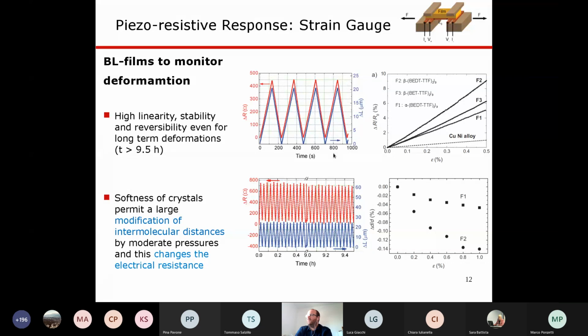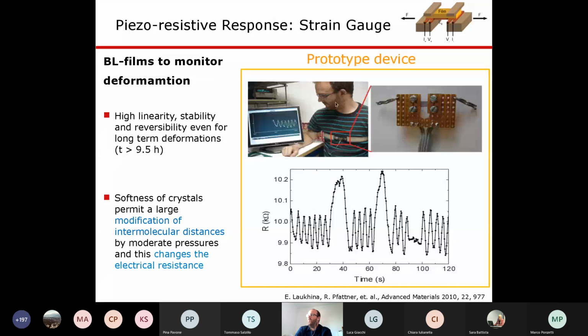So we were thinking about applications, and we developed a first prototype. That's me almost 10 years ago, where we mounted a small piece of these films between copper contacts and then mounted it on top of my chest. And we tried to record, or actually we succeeded in recording, my breathing rhythm. So in these first few cycles, I was breathing normally. Then I took a really big breath. Then I was breathing normally. Then again, a really big breath. And then normally, and then I stopped breathing.